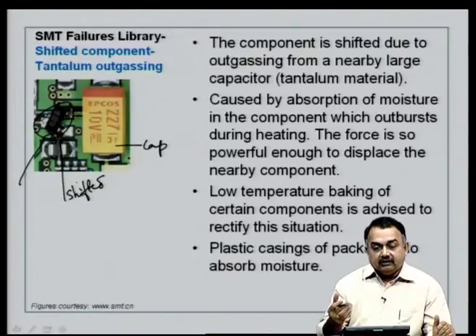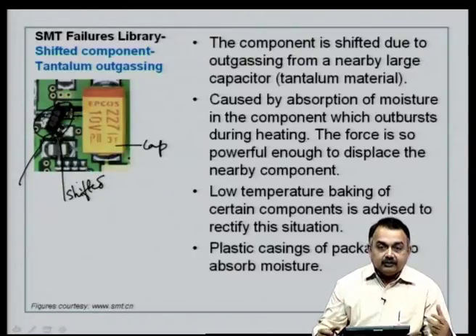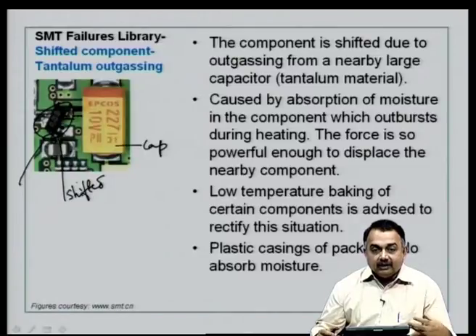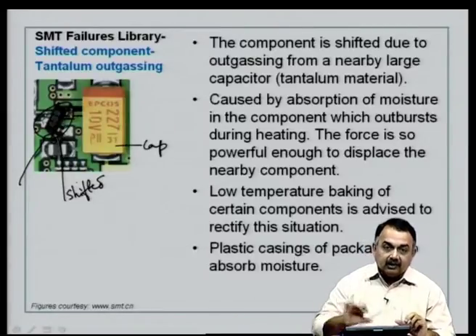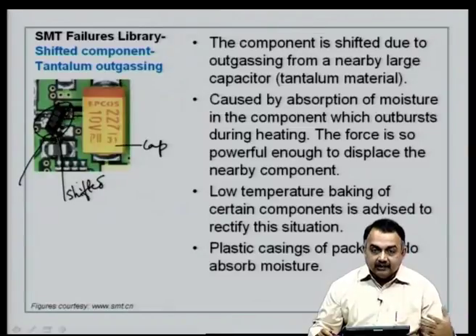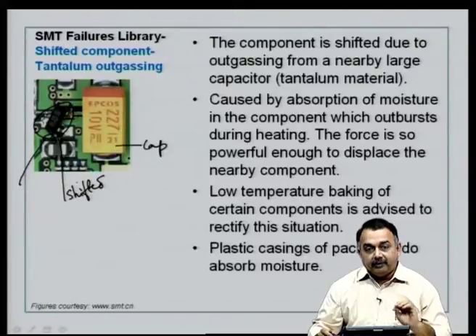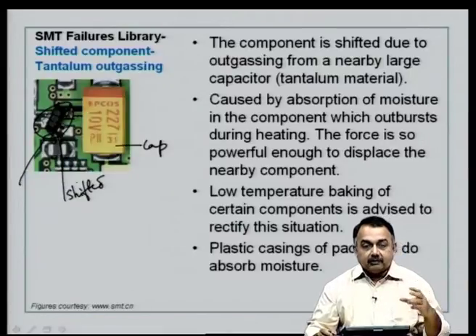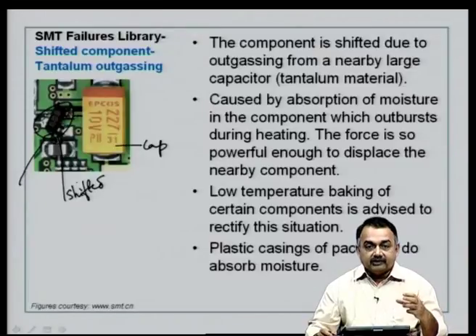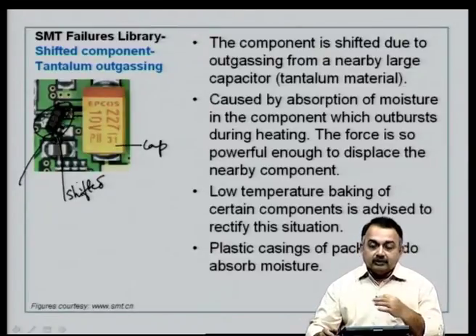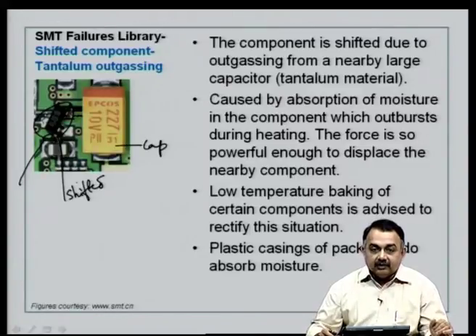The reason is simple. The capacitor has absorbed moisture during its storage period. Now, what you have done is you have directly used the component without doing a preheating, and then during the heating of the soldering process, the water is being removed from the component. There is an outburst of gases, there is outgassing, and this is so powerful that it displaces the nearby small component. How does it displace? Because the small component is actually swimming in the solder paste during the reflow process before it is cooled. So, it is very easy to displace the nearby component if it is lightweight.